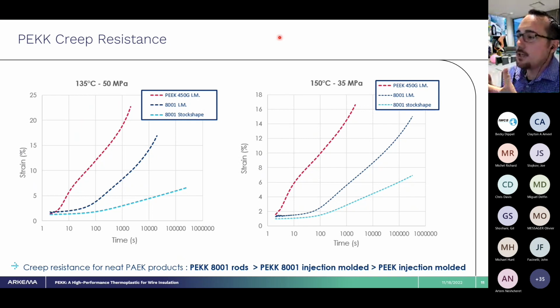We've got PEEK and PEKK at both 135 degrees C and 50 MPa, and then 150 degrees C and 35 MPa. What you're going to see is the same trend: for PEEK, you'll see an increase in elongation or strain on the order of minutes, whereas for injection molding, it pushes out further to about hours. And for the stock shape, you'll see an even longer time. So really good creep properties relative to some of these other materials in the ultra performance, high performance thermoplastic space.